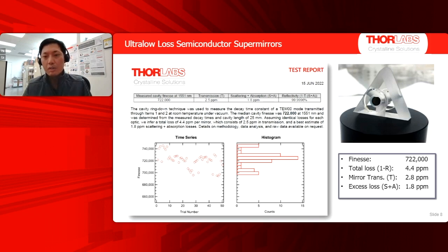And here we see that the finesse we achieved was above 700,000, and that corresponds to a 1 minus R of about 4.4 ppm. There's a small typo here. The mirror transmission was 2.5 ppm, and the excess loss was 1.8 ppm. So that's what we have been able to achieve, the very highest finesses that we've been able to achieve.